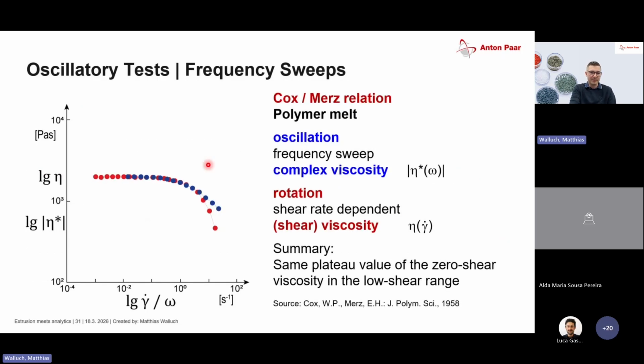So in red, we see shear viscosity, and in blue, we see the oscillatory viscosity, and we can see some differences. Why is that? For the very low shear rates, it is beneficial to perform shear tests over oscillatory tests, because oscillatory tests would take very, very long at very low frequencies. Here you get data within a reasonable time, which is not possible with oscillatory tests. But on the other hand, we see that the curve of the shear viscosity goes down much, much earlier than the complex viscosity in oscillation.